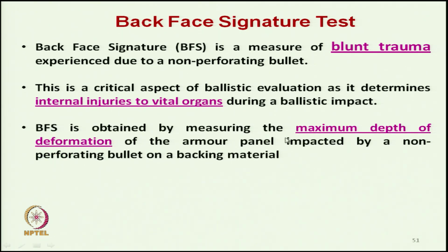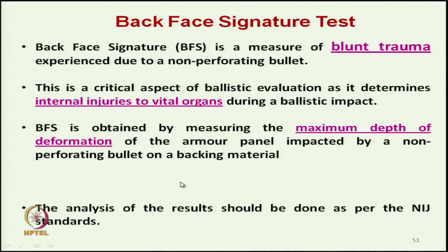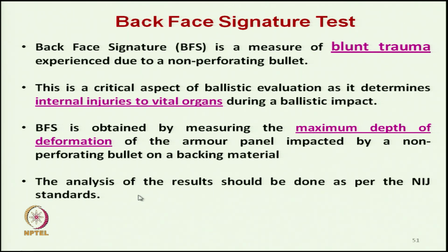BFS is obtained by measuring the maximum depth of deformation on the back side of the armor panel impacted by a non-perforating bullet. The analysis of results should be done as per the NIJ standard.